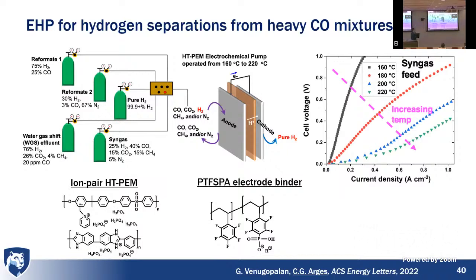And what was great about this system, because we can go to higher temperature, is that at the higher temperature, this ion pair, the acid doesn't evaporate from there. We don't have acid in the electrodes. We can operate at higher temperature. And then as we operate at higher temperature, we can pull more current, which is the rate at which we're purifying hydrogen from the hydrogen pump. And nobody had done this with large CO contents over 3% before. And we did it at 40%.